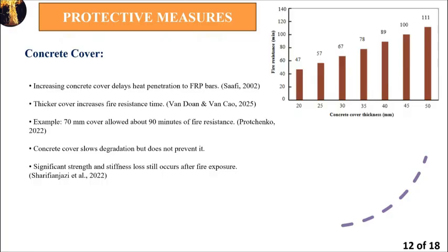So the most important point you should get is that increasing concrete cover is an effective and simple protective measure. It improves fire endurance time, but it cannot fully stop strength and stiffness degradation during prolonged fire exposure.